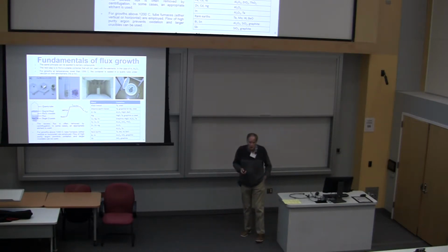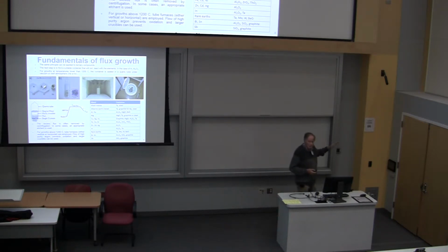Cerium cobalt, so in your periodic table, the cobalt column is cobalt, rhodium, iridium. And so the question was, why didn't cerium cobalt indium 5 come out also? Well, it turns out, which proved to be in many ways the most interesting compound in the group, that the cerium cobalt didn't come out because we weren't taking the melts to low enough temperature.